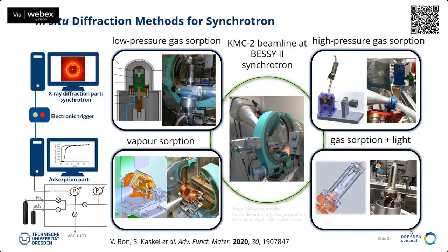Just to give you an overview, we developed some methods for the synchrotron, especially X-ray diffraction methods, and other authors developed similar methods, but the specialty for us is that we have a special dome architecture where the sample is located in the beam, and then you can dose a gas to it. You can measure a full gas adsorption isotherm on the sample. You can also expose your sample to vapors and measure the powder diffraction patterns. We also developed experimentation for high-pressure gas adsorption.